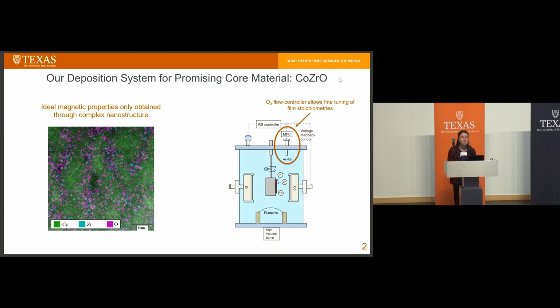So in our project, we're focusing on a really promising core material for high-frequency power conversion. It's cobalt zirconium oxide. In the literature, it's supposed to have these amazing properties for high-frequency power conversion, but there are two catches. One, like many core materials, it's typically sputtered at very slow rates. And the second is, in order to achieve all these nice properties that we want, the deposited films have to have this complex nanostructure that you can see in this TEM image. It consists of these nanoscaled cobalt grains separated out by this amorphous zirconia matrix.